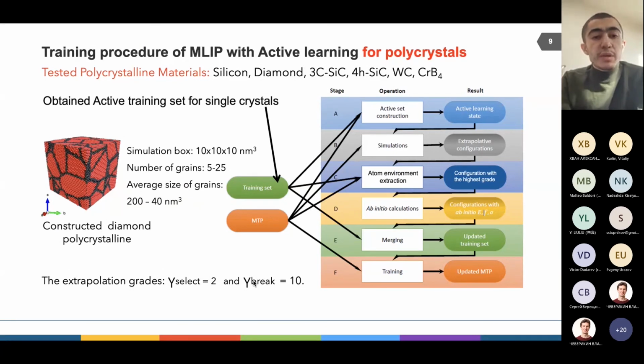Here you can see the procedure of active learning for polycrystals. In this case, as the initial active training set, we use the training set which was obtained for the single crystal. And we add some extracted atomic environments in the polycrystal with the highest extrapolation grade to our training set, and improve and obtain our moment tensor potentials for polycrystals.